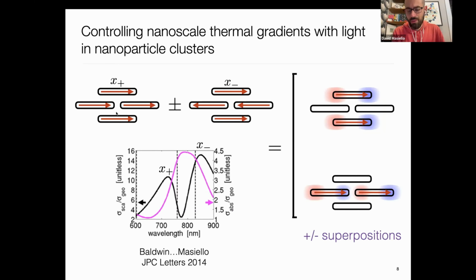And four gold nanorods, of course, when brought together, form four hybridized plasmonic modes, two of which are bright, two of which are dark. The two that are optically bright I'm showing you here. That's the all in phase mode and the out of phase mode here. There are two others that are optically dark that I'm disregarding. And so we had this idea that if we could drive optically linear combinations of these hybridized modes, we could create under CW illumination states of this coupled plasmonic system that localized either on the outer two or the inner two rods. You can just take plus minus linear combinations in your head to see that.